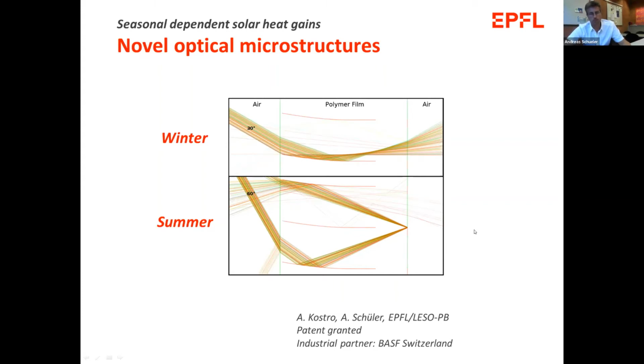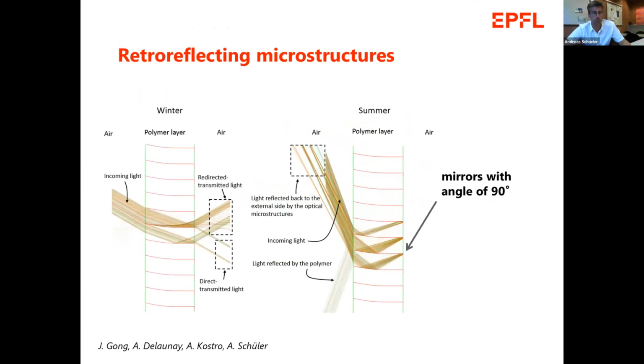So we came up with this geometry after a couple of simulations. Our PhD student André Kostro programmed a simulation tool, and we ran a large campaign of simulations in order to find this geometry. In between, we have novel geometries with our PhD student Jin Gong. So here we propose to make the structure a little bit longer, make the mirror from one structure basically, and have this 90-degree angle here in the corner. And then we would even send this sunlight back to the sky in the summer situation. So we would have less heat in the street canyon, and we would also have less glare in the street canyon in our cities.